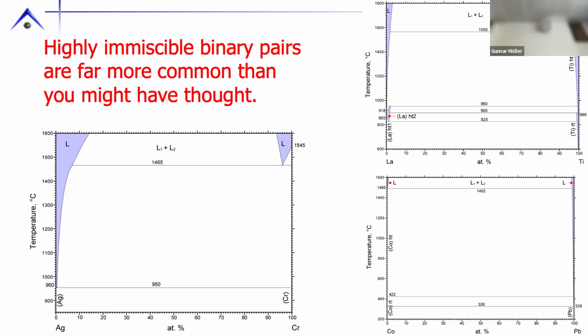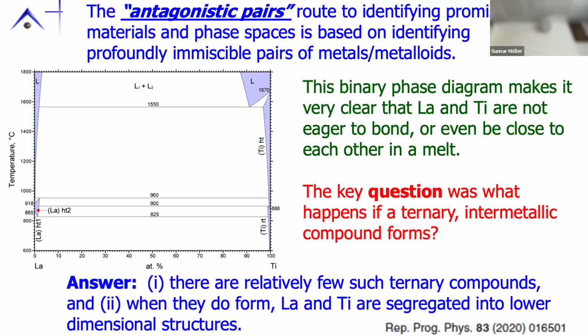Okay, so for many years, these were turn the page. This is inauspicious. I want to grow out of a liquid. There's no liquid. Not good for me. And then I realized that was a prejudice that was missing an important insight. I finally got to the point of asking myself, okay, lanthanum and titanium, lead and cobalt, they don't like to mix. Can I find a ternary compound that forms? Okay, and remarkably, this is a question that had not really been asked. Okay, so what I found is there are relatively few ternary intermetallics associated with such immiscible or antagonistic pairs, but when they do form, you end up with the third element coming in as a NATO peacekeeper, separating them. Okay, so let me show you some examples.